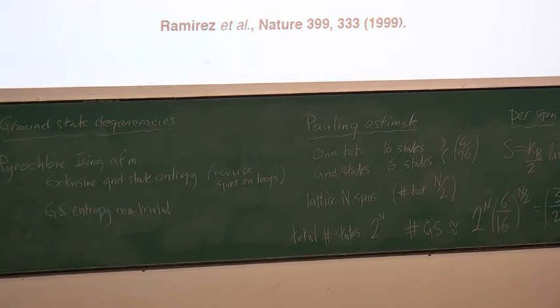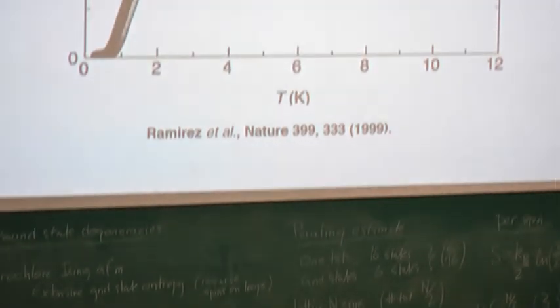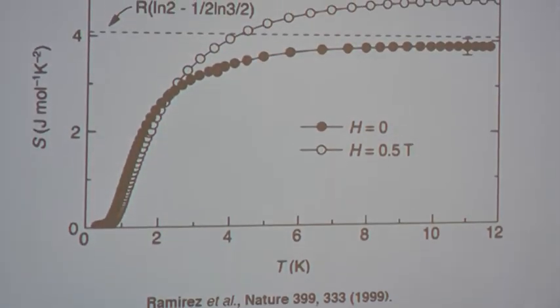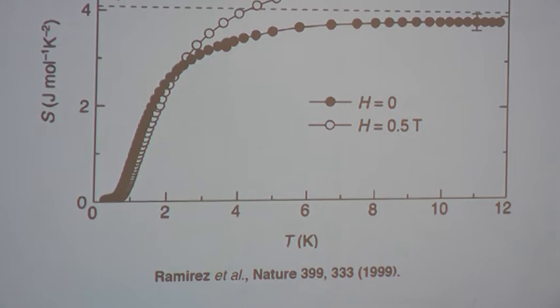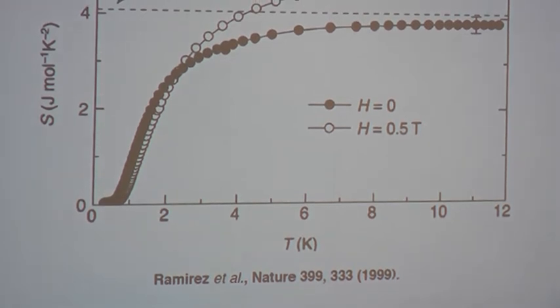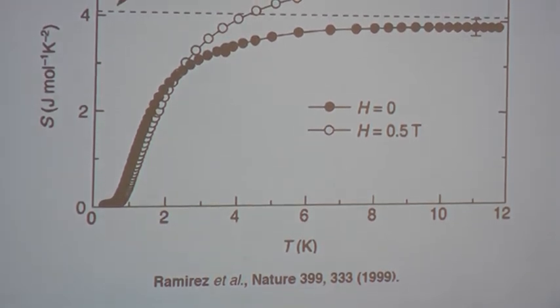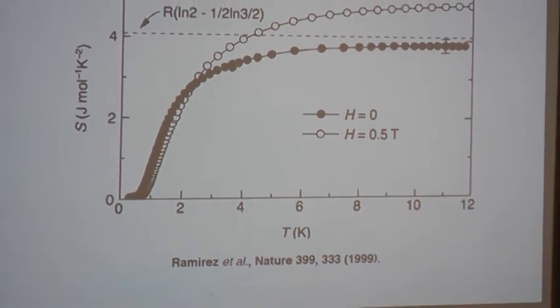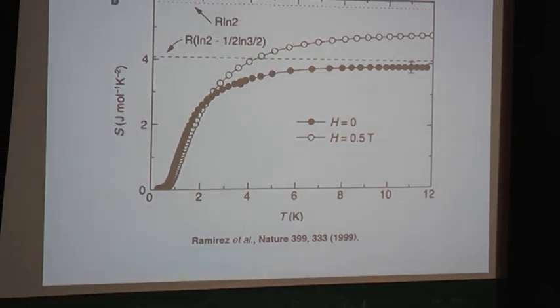And rather than getting a loss of entropy when we cool down of log 2 per spin, or R, the gas constant, log 2 per mole, we find that the entropy loss is reduced by just this ground state entropy. So my point here is that the degeneracy, which comes from frustration, has consequences which you can observe rather directly in the experiment.